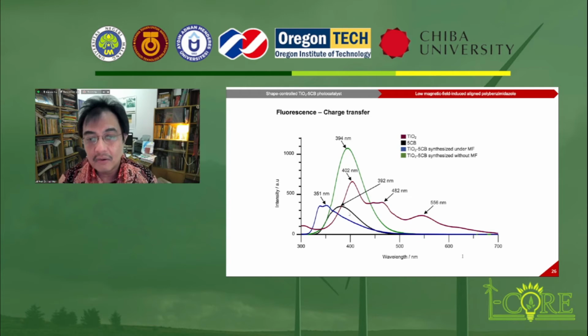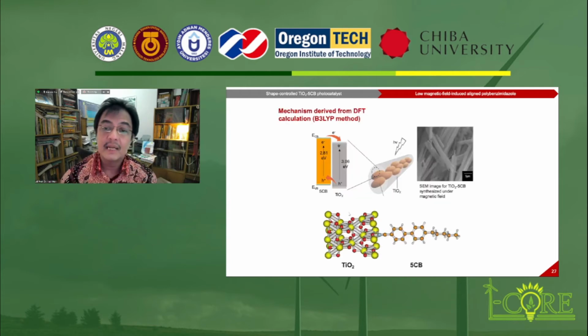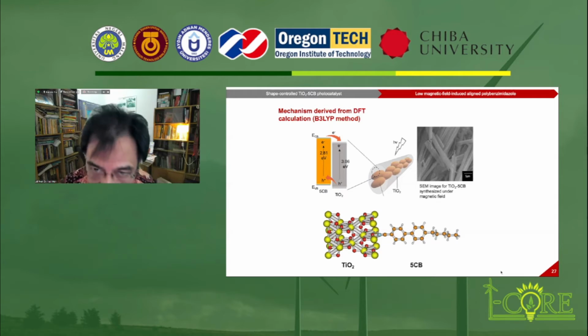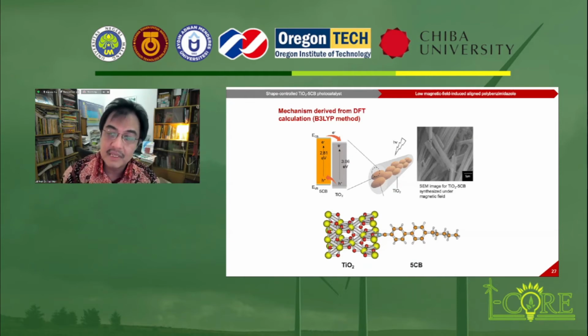And this is the result of the DFT calculation. It can be seen that there is a charge transfer from the valence and conduction bands of the liquid crystal to the titanium. This can only happen if there is an interfacial interaction between the liquid crystal and the titanium. Okay, now we change the topic to low magnetic field induced aligned polybenzimidazole.